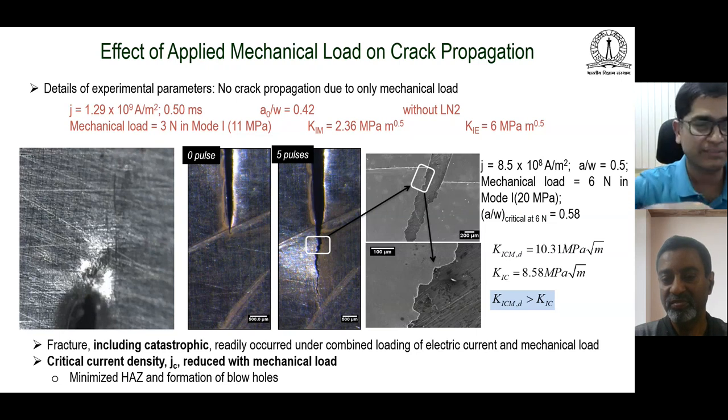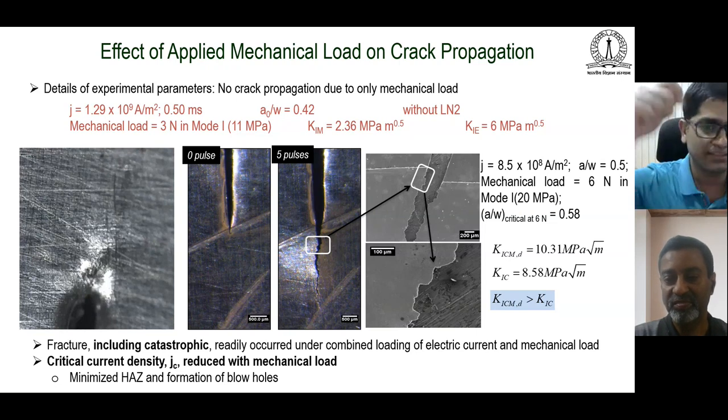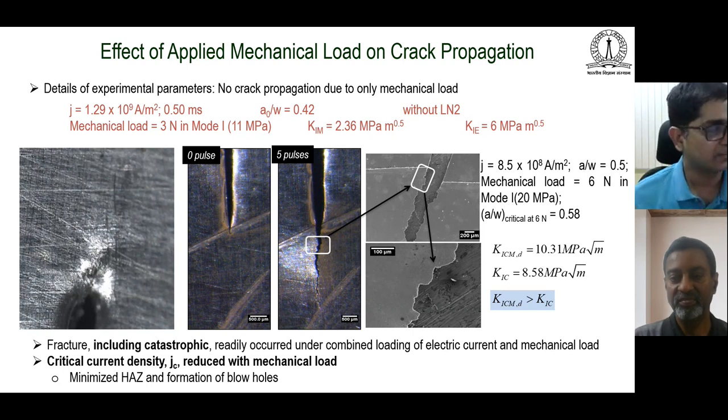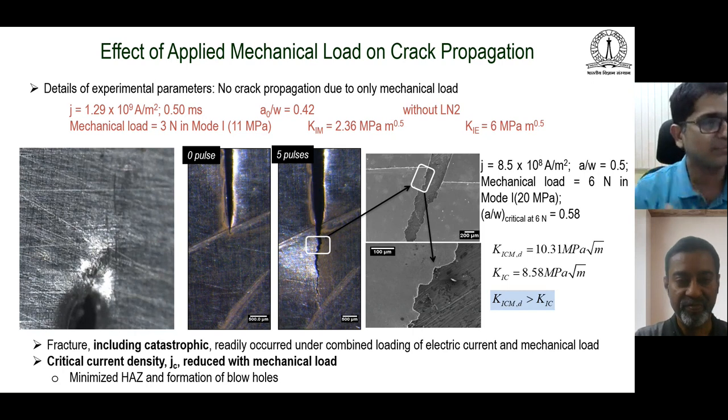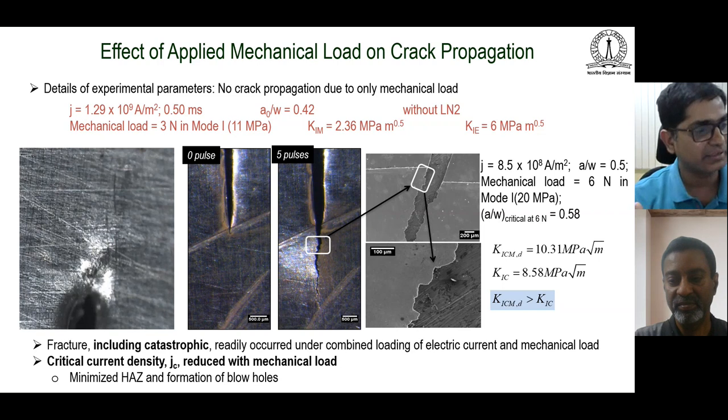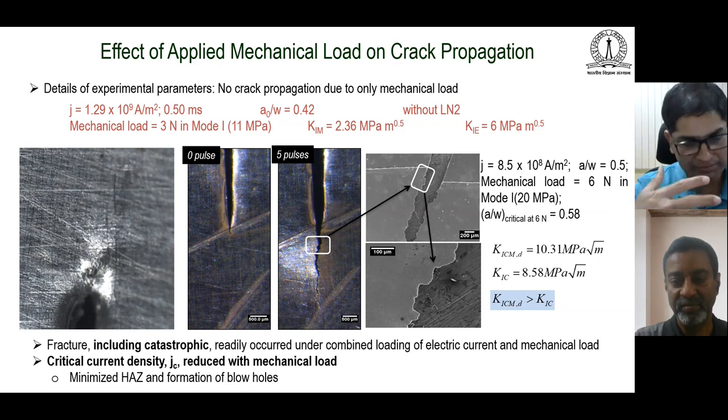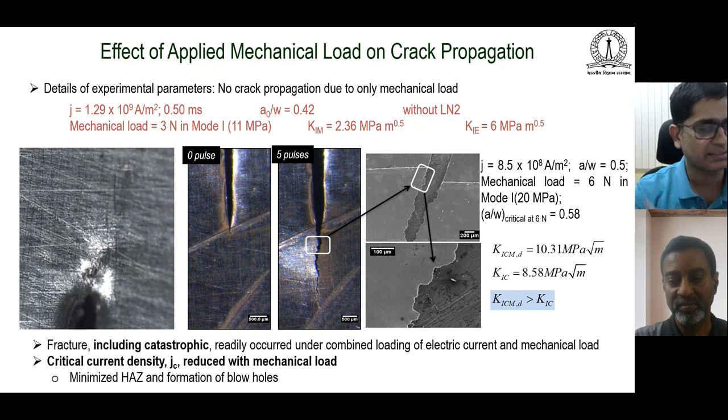So when we are passing the current pulse, there's a large change in the electric field in the beginning, because we are passing a square pulse. So the change in the electric field is very rapid. That leads to the generation of a magnetic field. But the magnetic field is also changing, and a change in the magnetic field will then induce current, right? Essentially, the material is resisting the injection of the current, and it is doing that by enhancing the eddy currents. So the net current actually flowing through the material is much smaller than what you are trying to pass.